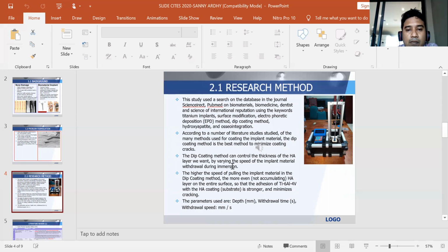According to a number of literature studies, of many methods used for coating the implant material, the dip coating method is the best method to minimize coating cracks. The dip coating method can control the thickness of the hydroxyapatite layer we want by varying the speed of the implant material withdrawal during immersion.